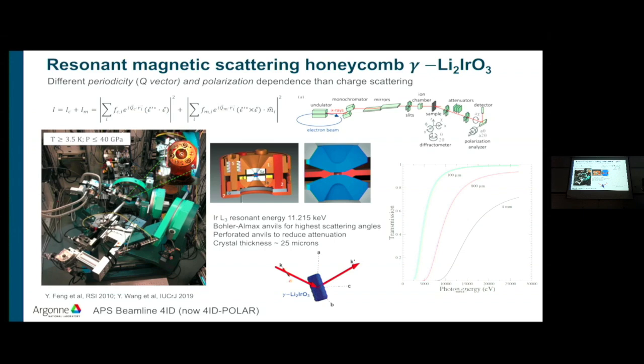And we have to work at resonance, and the iridium L3, which is a 2p3/2 excitation, is 11 kilo-electronvolts. It's rather small energy for high pressure work, because the absorption of the diamond anvils in the high pressure cell is quite significant, as you see here. Typically you have 4 millimeters of diamond, and at 11 keV, this is the transmission of 4 millimeters of diamond. You're down here. So what we do is we use diamonds that are laser drilled, partially perforated, to reduce the attenuation of the X-ray beam in the diamonds. And your crystal has to be thin enough, also about 25 microns, for the X-rays to go through the crystal.